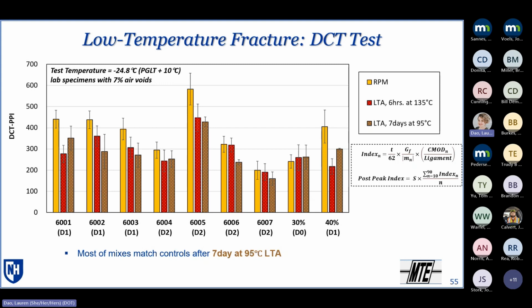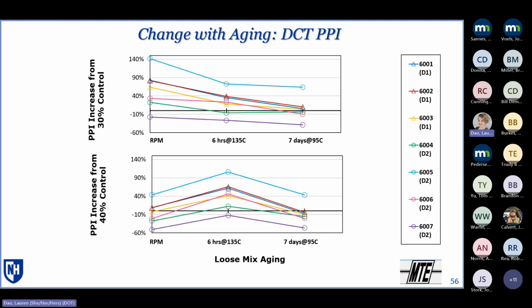So you can see most of the mixes are either better than or matching the controls once we get to that long-term aging. And we're seeing what we expect in terms of the decrease with aging over time. And again, you can see the plots here with respect to the 30% and the 40% controls with those different aging conditions.